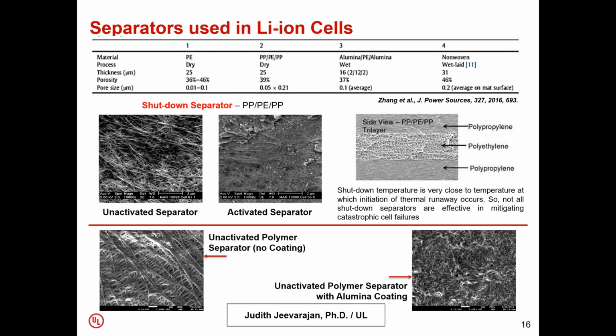And the one on the right is an activated separator, where the polyethylene has actually melted. Polyethylene melts at about 130 degrees C. And when it melts, it shuts down the pores in the separator. And so the ions are not allowed to move between the two electrodes, thus making the cell safer.